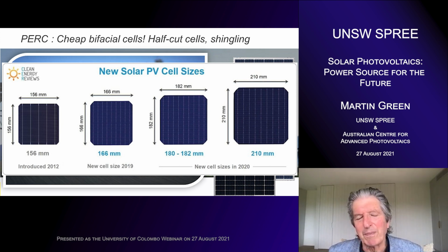And because PERC has allowed you to cut the cells up quite simply, because there's patterning done on both the front and the rear surface in the cell fabrication, it's easy to design them to be cut in half. For a long time, a 6-inch square wafer, 156 millimeters, was the industry standard. But just over the last couple of years, with the uptake of PERC, people have realized that they can cut the PERC cells into smaller wafers quite easily. So that's encouraged the use of bigger wafers.